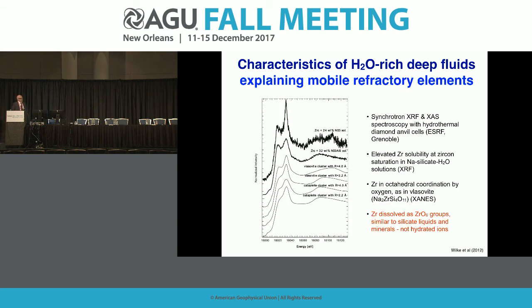And I'll just leave you with a final thought, and that is that if you have in the aqueous phase sites that are similar to those in minerals and melts, that are essentially sites coordinated by oxygen rather than ions that are coordinated by H2O molecules as in deep, shallow fluids, then you have opportunities to dissolve much more nominally refractory constituents like zirconium.